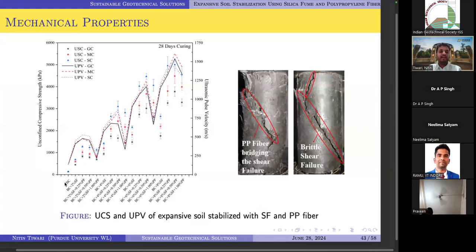So you can see I'm just presenting one result with the 28 days curing and all the methods of curing we use. So there will be some limitation, but you can see initially we had very little, 130, 140 kPa of unconfined compressive strength, and we achieve almost 5,000 kPa of strength, which is a huge increment, with the 8% silica fume and 0.5% and 0.25% of polypropylene fiber.